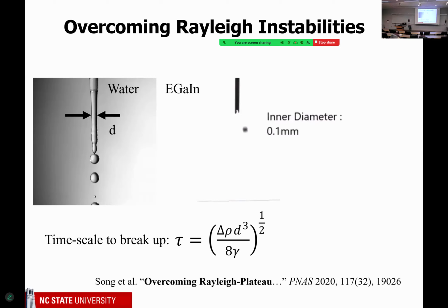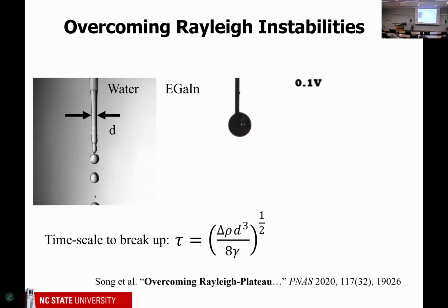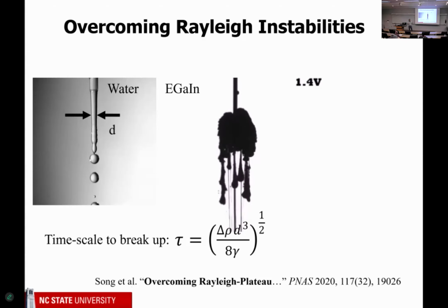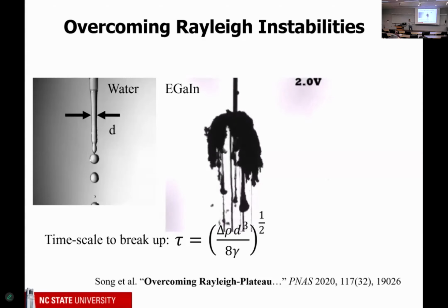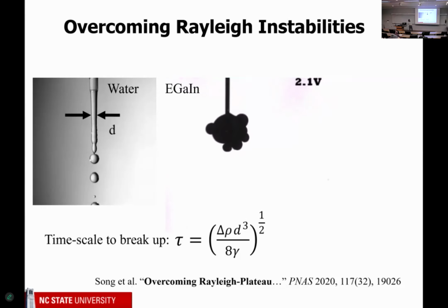overcome this. So here we have a video where we pump liquid metal out of a nozzle that's 100 microns. That's the size of a human hair. And so we start applying a potential, 0.3, 0.4 volts. You see the droplets get smaller and smaller due to the smaller tension. And then at that same voltage we see fractals, and it comes out as a wire. Now, if you go a little bit too aggressive and you jack up the voltage, you end up with this crusty skin, and it looks like candle wax. And we wanted nothing to do with that, so we did not study it.